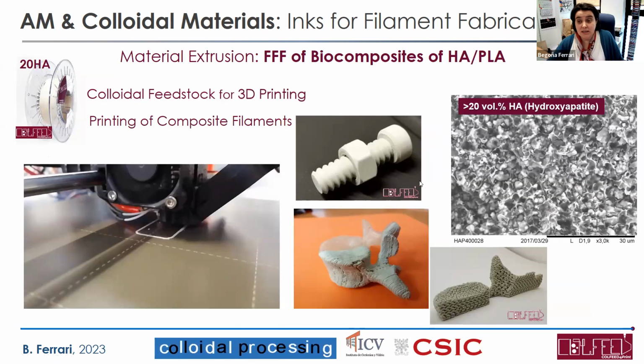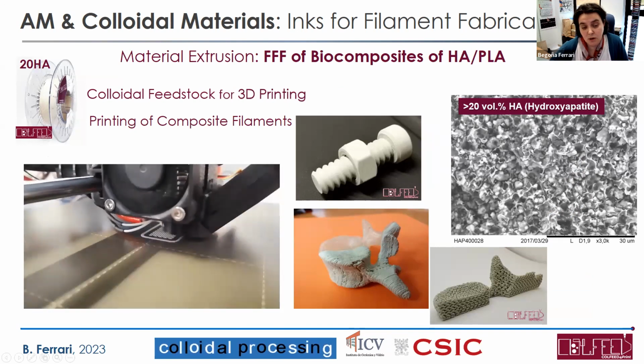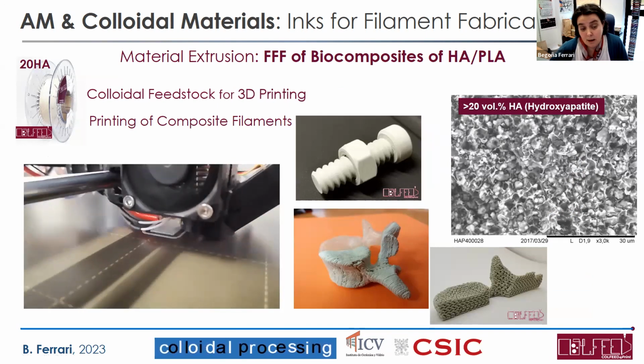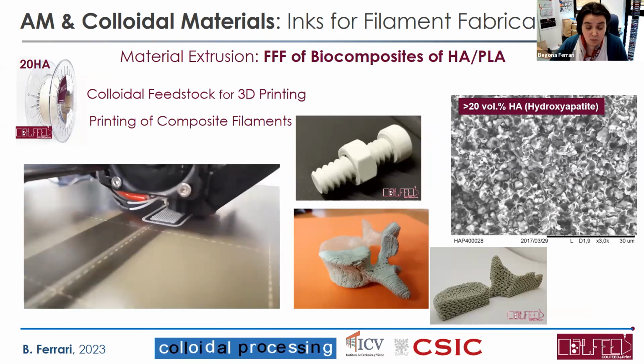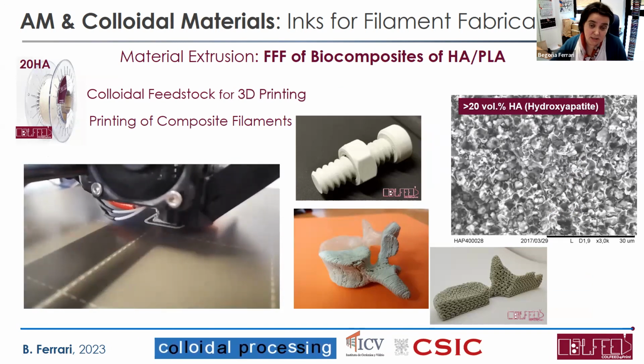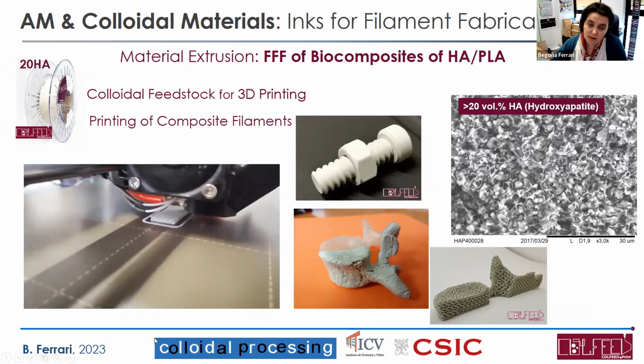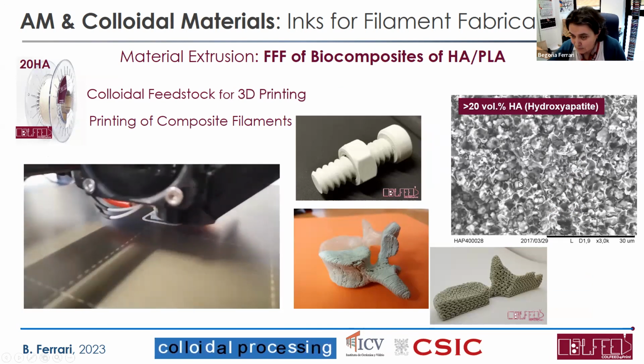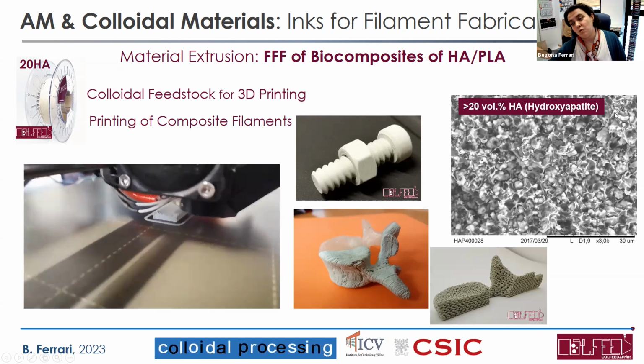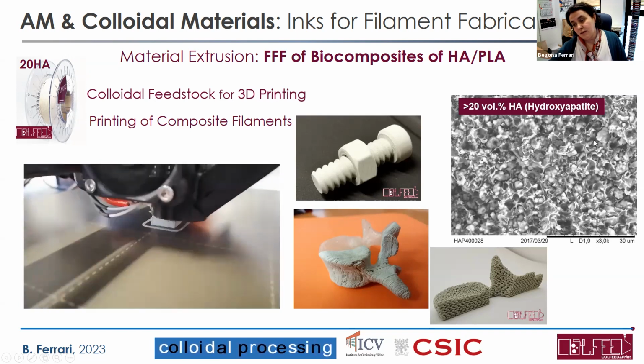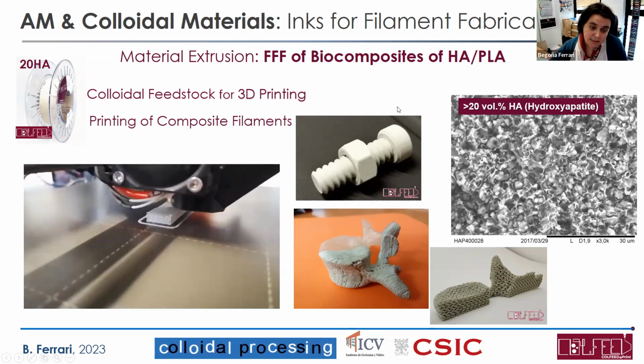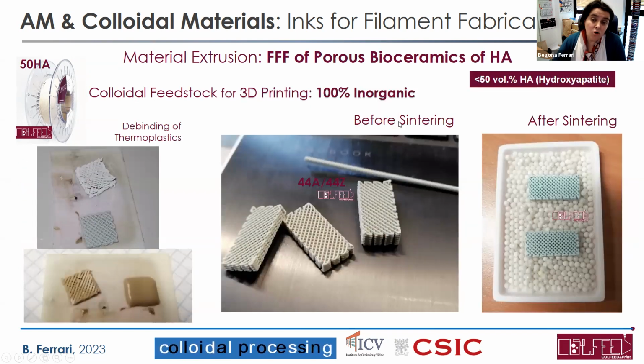In this case, for example, we are using hydroxyapatite inside of the material. You can see we can print with a regular desktop printing machine, right? Different kinds of structure. You can see all the small hydroxyapatite particles surrounded by the plastic, right? This is the result of wet mixing. And of course, we can achieve 50 volume % hydroxyapatite inside of our filament.